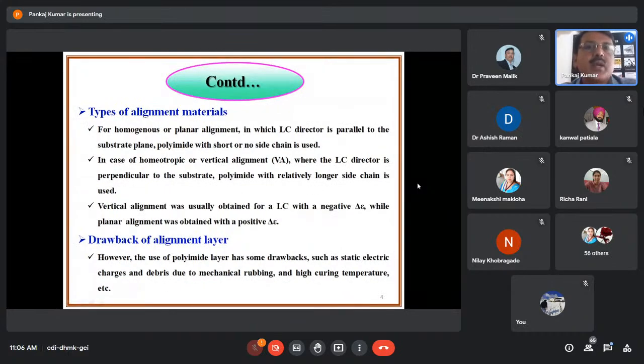So types of alignment of the materials: for homogeneous, or we also call it planar alignment, the liquid crystal director is parallel to the substrate plane. Polyimide with short or no side chain is used. Substrate plane means the liquid crystal molecules will be in the plane of the surface. In case of the homeotropic or vertical alignment, the liquid crystal director is perpendicular to the substrate, and polyimide with a relatively longer side chain is generally used to make the vertical alignment.